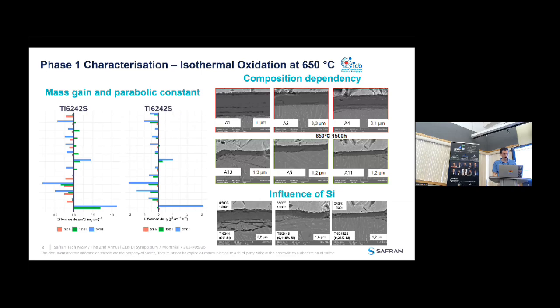actual resistance. We also did study the oxidation behavior. The idea there, it's another part of the compromise, right? Is to this time be on the left side to minimize the mass gain due to the intake of oxygen in titanium alloys because they love oxygen. So either judged by the mass gain or the parabolic constant of oxidation. So 2 ways to judge the kinetics of oxidation. And we evidenced some obvious compositional dependency on the delamination, the thickness, the composition of oxide layers with the key influence of silicon. But basically we found rather reasonable observations that didn't contradict the literature.